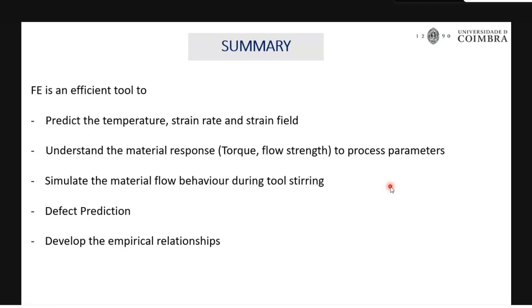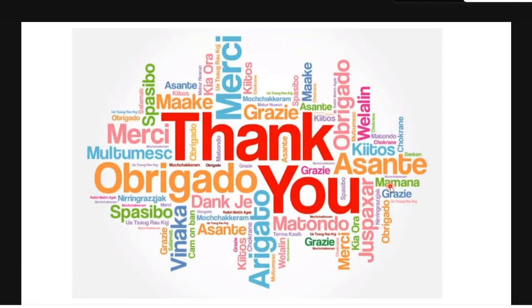Previously it was believed that the yield strength is an important parameter, then it was identified that flow strength is an important parameter, then that strain rate sensitivity is an important parameter. This only happened because of the finite element analysis, because with respect to the experimental condition, it is not possible. So you can explore more about the friction stir welding process with the FE, and you can take it to the industry. And that's the end of my presentation.